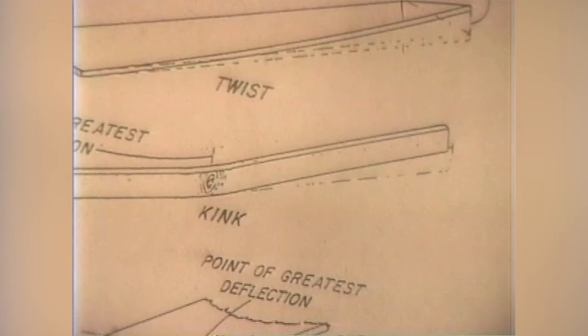FAS regulations are strict about how much pith is allowed because of the instability it causes. Another thing that can cause bowing is heartwood versus sapwood shrinkage: you're going to have more moisture content in the sapwood, and it's going to do more shrinking and can cause those problems. Kinking occurs where we have more dense wood around a knot that does not shrink as much as the less dense wood further away, and that can cause major deflection.